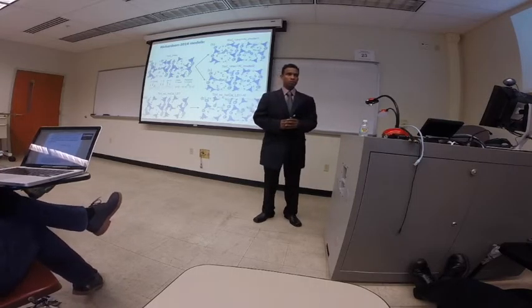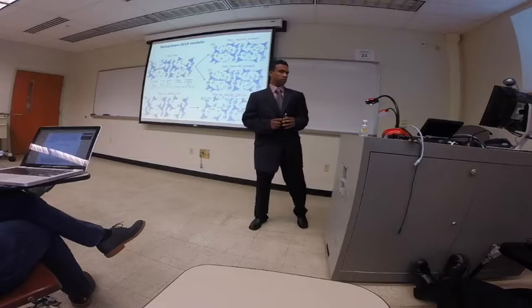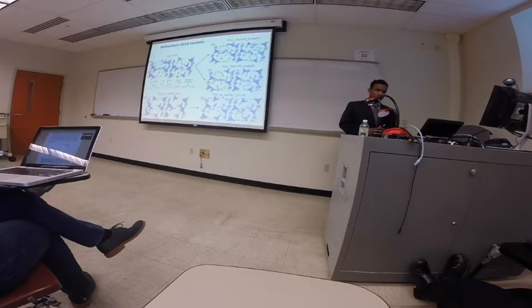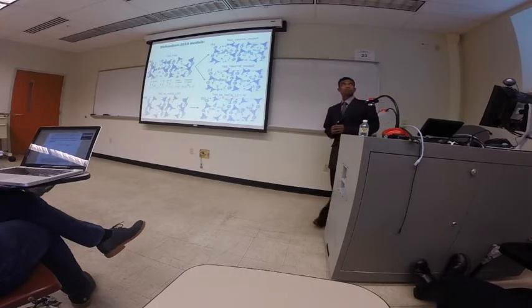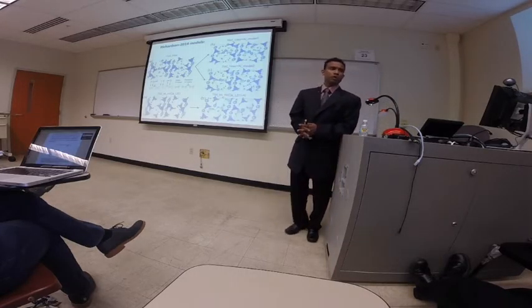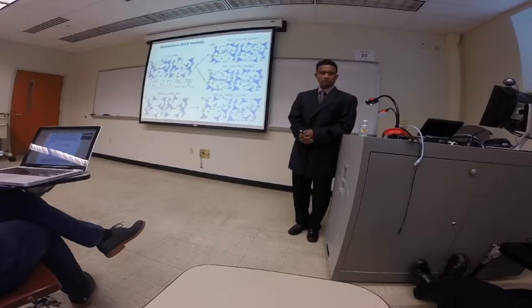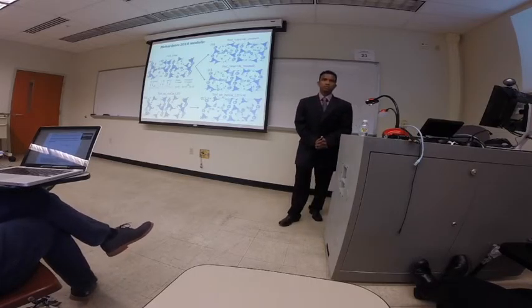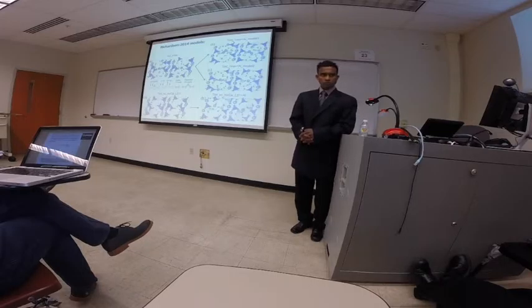So I had maybe one other question. Regarding the calculations that you did, this total bond order density, basically what that comes up with is a single number that characterizes the overall bond strength associated with the crystal. But you mentioned that a lot of the different crystals obviously have some sort of internal structure. They're not necessarily isotropic, so there is a likelihood of differences in different directions, and there are layered structures. Two crystals may produce the same total bond order density, but have very different properties internally, just because they have different sorts of layered structures.